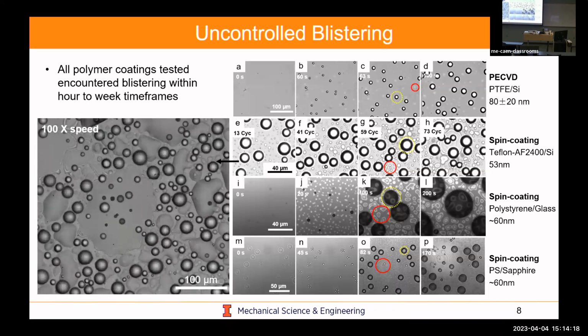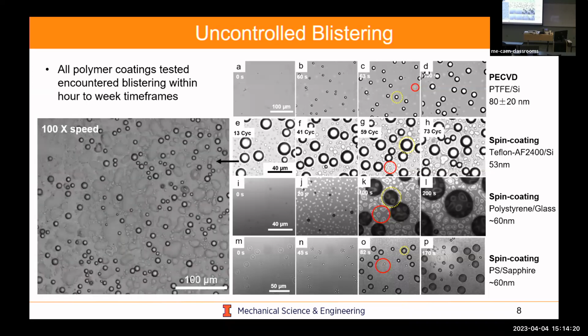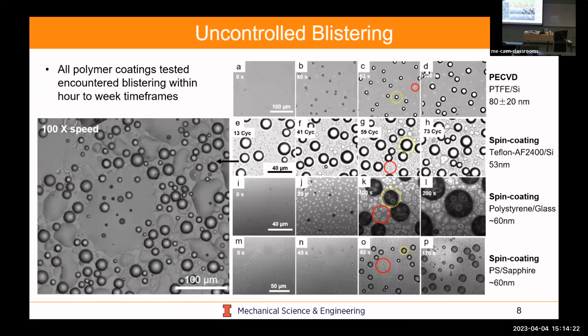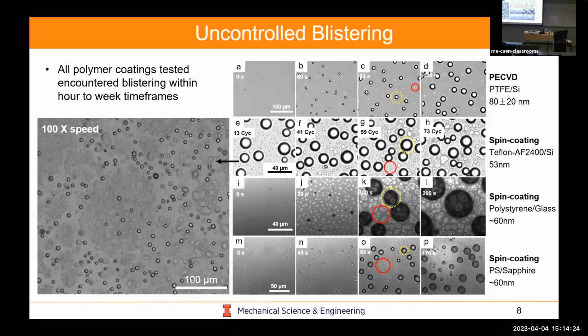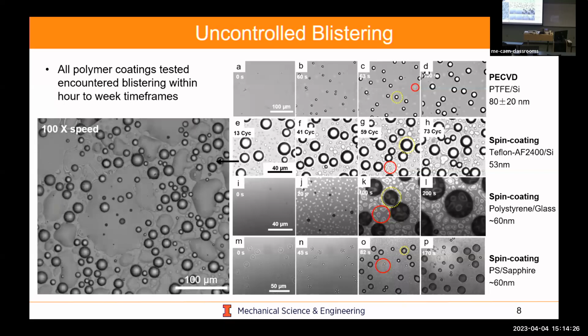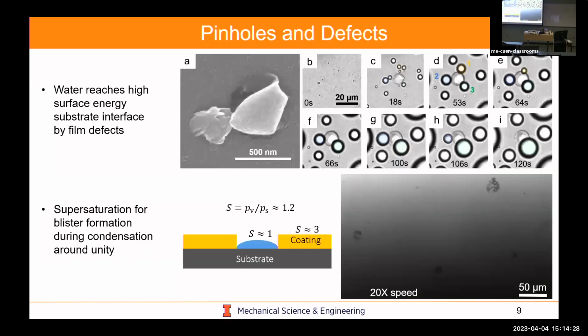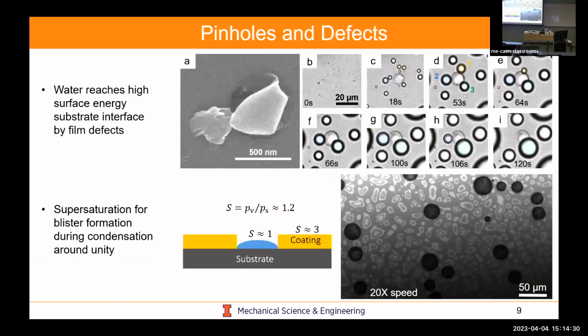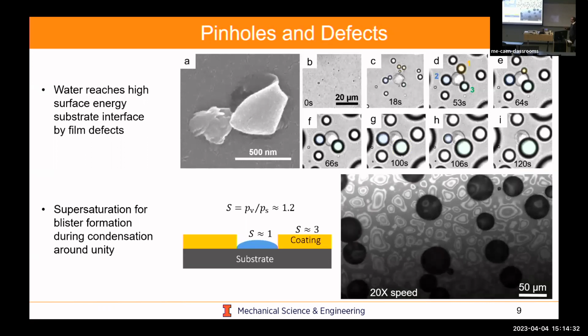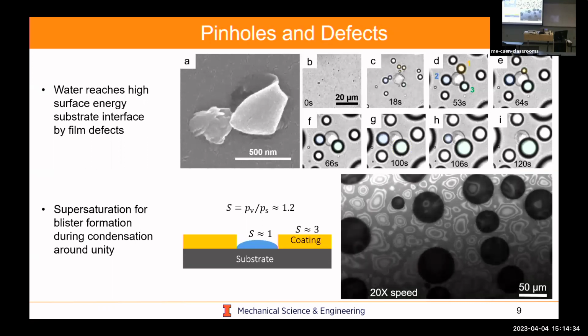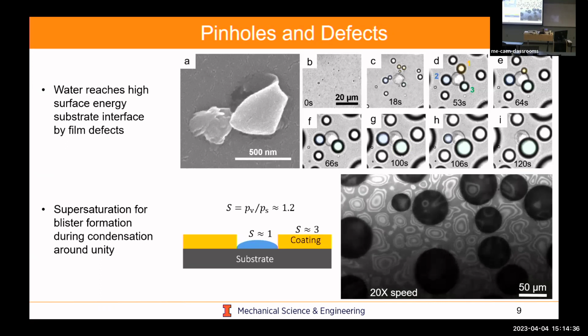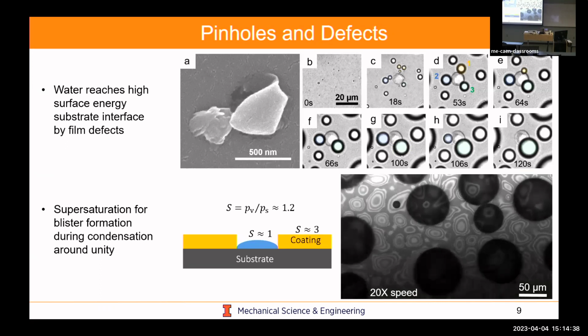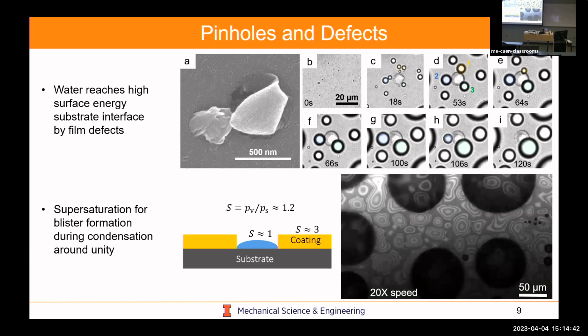And initially, this was great. We could actually get repeatable results in terms of failure, but this really was limiting us because we weren't able to tell what's actually going on and what's causing these blisters to form. And so one of the initial things that we discovered just by careful observation was there's probably the presence of pinholes. Whenever we deposit these, even if it's CVD, there are going to be some pinholes in the surface just because of dust particles or the processing steps.